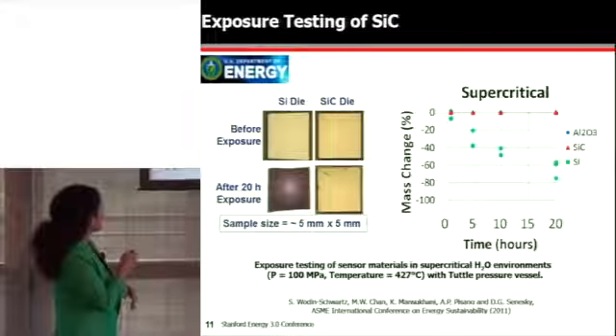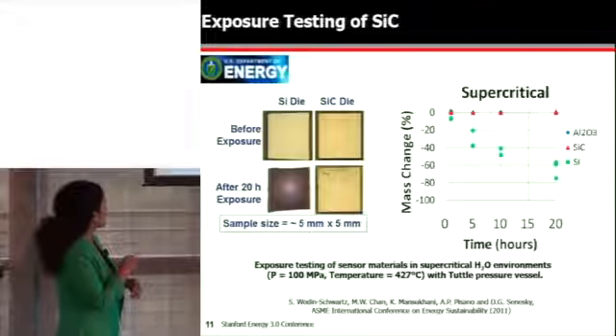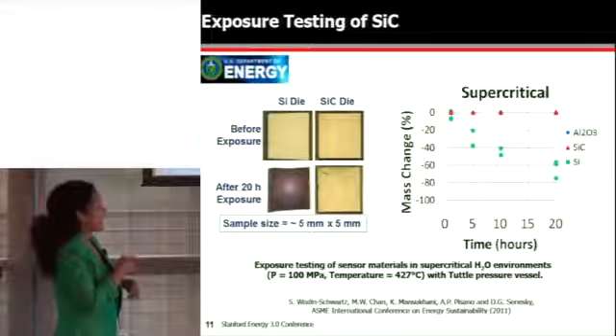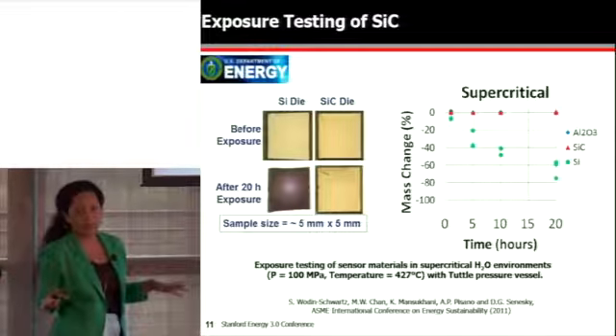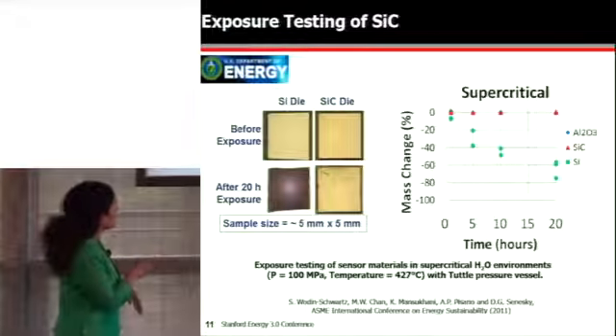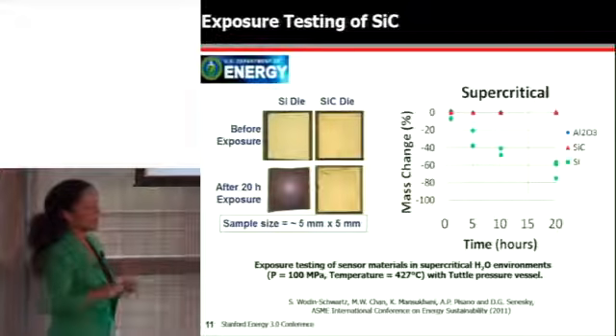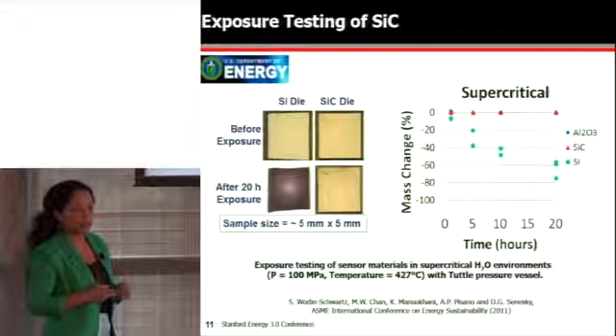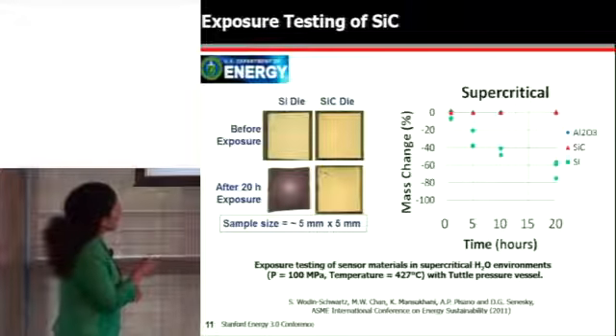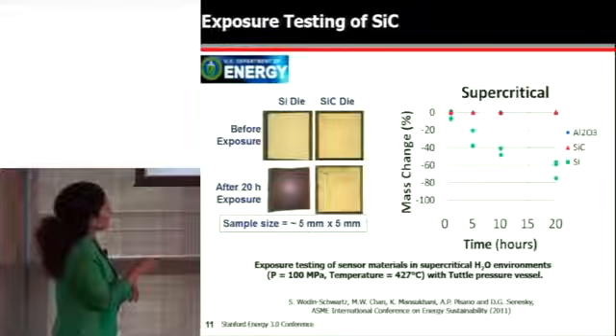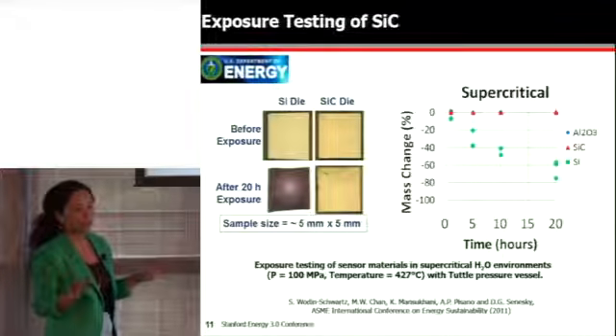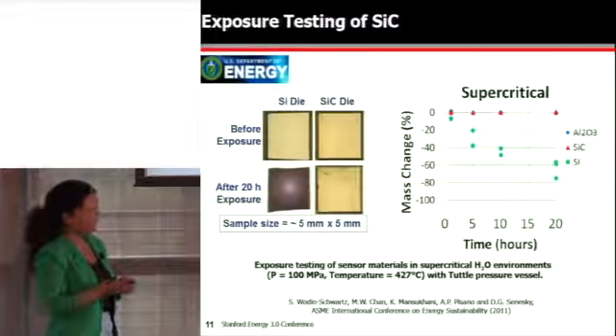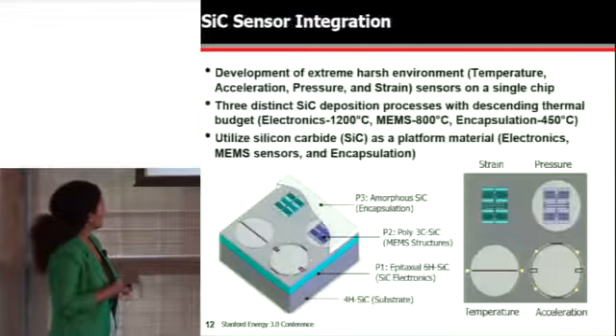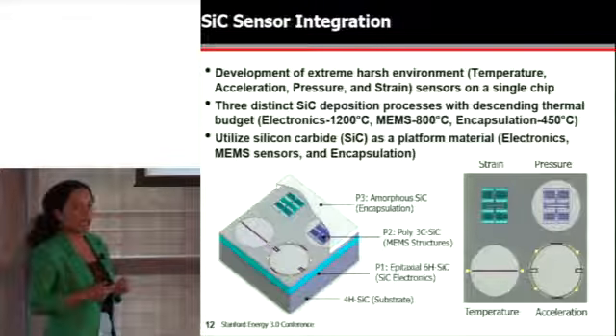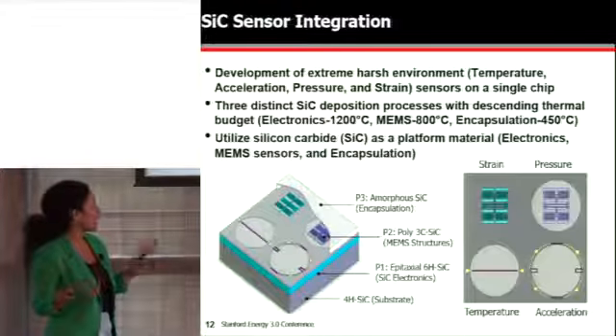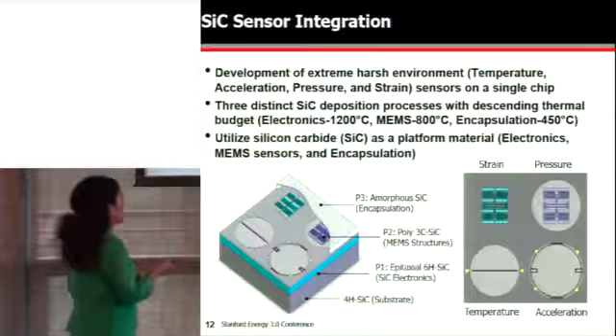We took some silicon chips, and before exposure, you can see the state of the chip, and then after exposure of 20 hours, you can see the silicon just starts to degrade due to chemical erosion, whereas the silicon carbide remains intact before and after the exposure test to supercritical water. Also, we're measuring the mass change. You can see the silicon carbide has no measurable mass change, so no erosion that we can observe through this measurement.